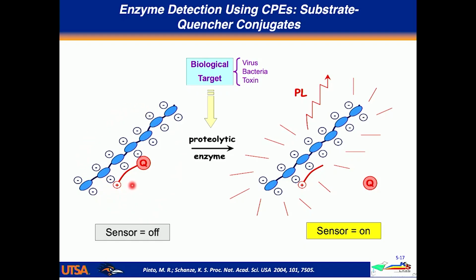And then when you add the target, in this case a proteolytic enzyme, that enzyme cleaves a bond, releases the quencher, and the fluorescence of the system turns on. The idea, again, remember, is because of the amplified quenching effect, you don't need to add very much of this quencher to the polyelectrolyte to essentially turn the system off. And that also means that you don't need much of the enzyme to recover the fluorescence.